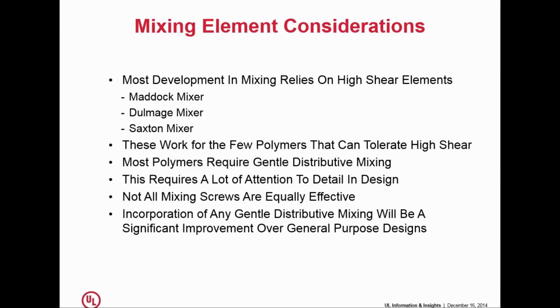But you're not going to be able to do it with materials like ABS, polycarbonate, polysulfone. You're going to need gentle distributive mixing. And that slide I showed you previously is what is designed to achieve mixing without getting too heavy-handed. And so this requires a lot of attention to detail. Not all mixing screws are equally effective. You've got to do your homework, and you may have to do some trials. I've gone into places where people say, well, we already have a mixing screw in there. And you say, yeah, but you're not getting the mixing you need. And we pull that screw out, and we put a different design in, and we get different results.